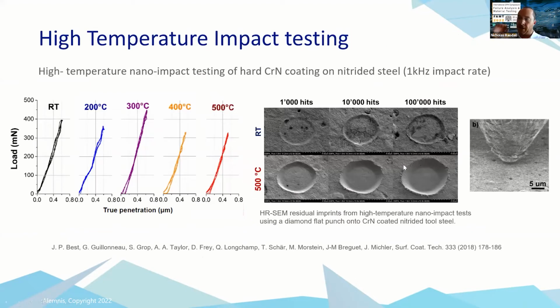Another way we can use the system is for rapid impact. So for shock testing, here we've actually got tests on a coating up to 100,000 hits with a flat punch, and at 2 temperatures, room temperature and 500. So we can see how the material reacts to repeated impact on the surface.